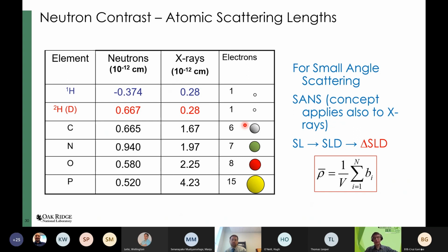So you already mentioned this one earlier. Scattering length density. We are sensitive to hydrogen in particular. Hydrogen and deuterium are very different, and because we are adding up the scattering lengths of individual atoms to calculate the scattering length density, that has another very beneficial side effect. If you take water, for example, with 2 hydrogens and 1 oxygen, the 2 negative terms and the 1 positive of oxygen almost cancel each other out. And for D2O, this large positive number adds to the oxygen.